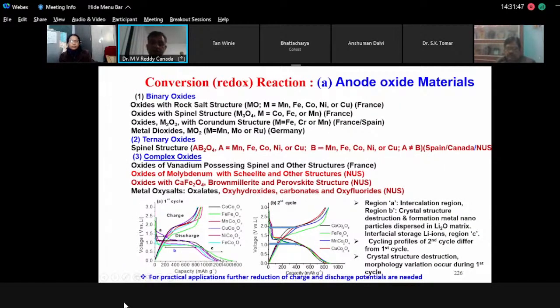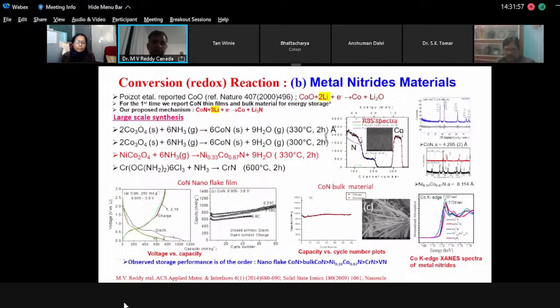The main challenge is how to reduce the voltage hysteresis, which is a big issue for this type of method. That's why we cannot use this particular material for commercial applications. Similarly with the nitrides, again, the 3 lithium can be reacted. The problem is the capacity reduction, what they call voltage hysteresis.